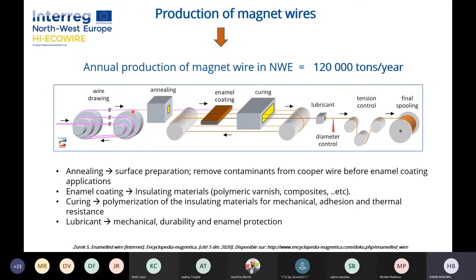The wire is passed through annealing systems for surface preparation, to remove any contamination from the copper wire before the enamel coatings. In this part, we have the enamel varnish, or enamel coating, that will be applied on the wire. Then the wire passes through a curing system for polymerization of the polymeric varnish, and also to remove all the solvents present in these steps. We can make different passes to control the thickness of the enamel coatings on the wires.